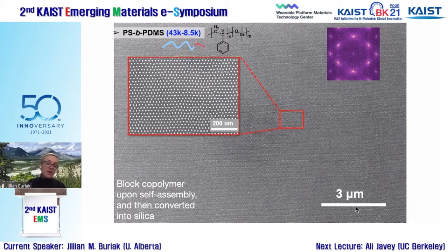And here's the fast Fourier transform. So this is a 3-micron scale bar. And so this is a particularly large two-dimensional grain, or crystal. But what we're not showing you is what you should always ask when you see this work, and you hope that authors put this in supplementary materials, is that you want to get a sense of how big these grains are, or these crystals, and what they do at the interfaces of where they meet.